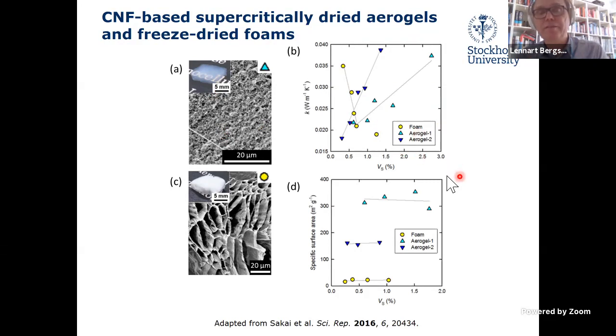This suggests some interesting phenomena. When it comes to the supercritically dried, they have a clear isotropic and relatively homogeneous pore structure. There you find the classic behavior you would expect: as the density of the foam increases, the thermal conductivity increases - the more solid material you put in, the thermal conductivity increases.